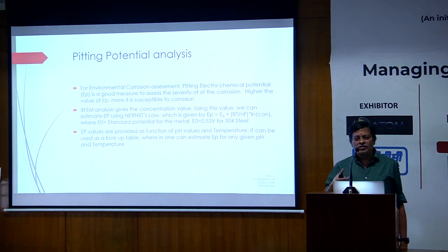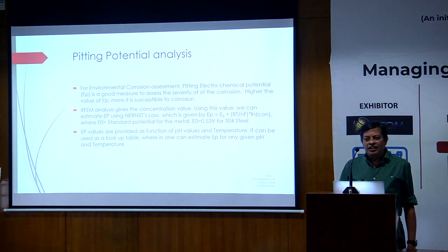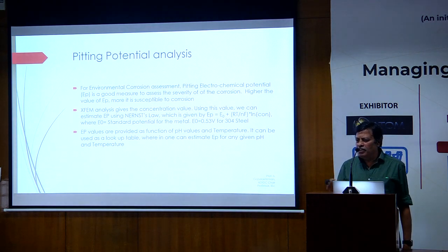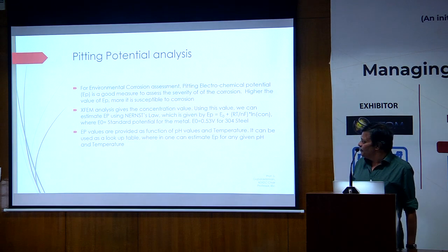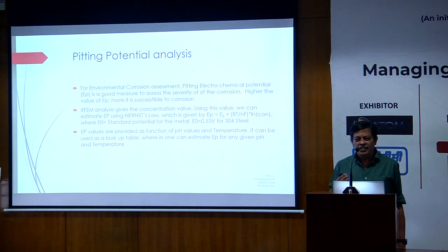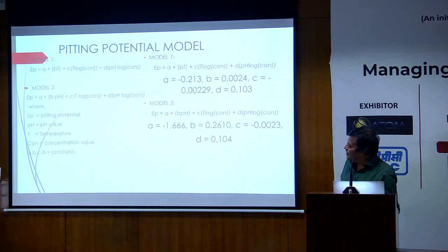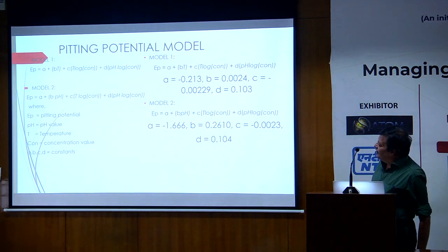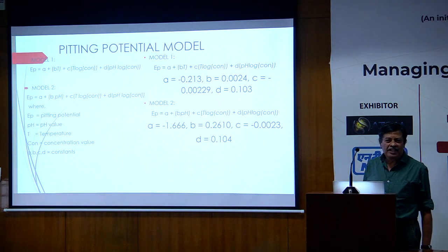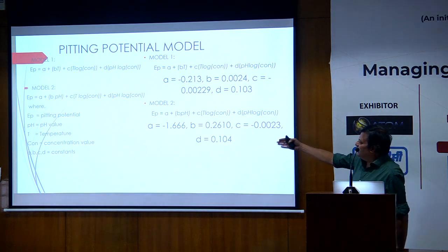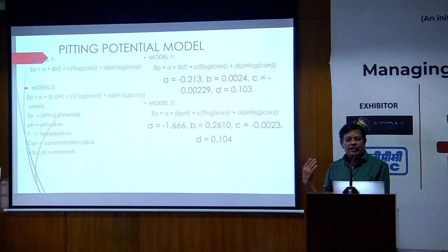That is, we can take the concentration coming out from my model and then generate the electrochemical potential, which is normally used in the field, using what is called the Nernst law, which is given here, and then generate a series of lookup tables, which is required for the industry. So here is an example. There are two models which we did. Using the values I've obtained from the model and the temperature and pH, I can generate the different electrochemical potential and empirical relations, so that we fitted two different models and then compared them with the experimentally generated response.